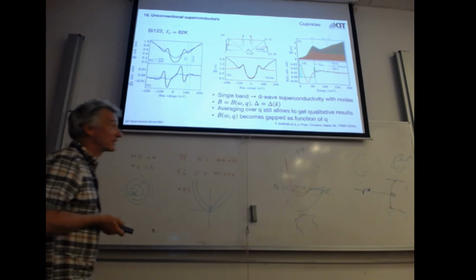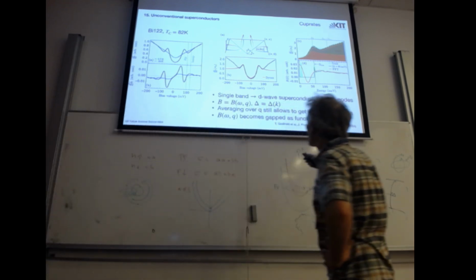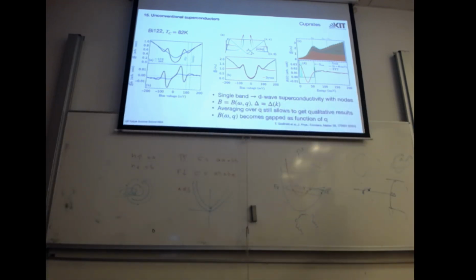Can we deconvolute it as well? The problem is there's only one band. So you have to have a change of the order parameter on the band. That means it must have zeros. Yeah? So the order parameter needs to change somewhere on the Fermi surface, and these are the nodal points. This one is the d-wave.